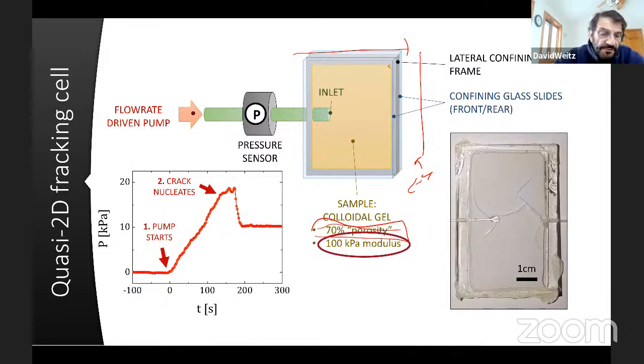So if we inject the fluid, this is what it looks like. If we increase the pressure as a function of time, we just use a syringe pump, and you see that we start injecting fluid, and we put a few kilopascals in. Roughly the yield modulus of the sample, and then a crack will nucleate and will flow, and we'll study the behavior and the propagation of the crack.